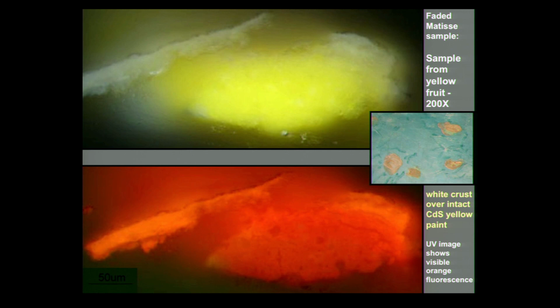And then here's a look at a tiny flake of paint that we removed from one of the yellow fruits in the tree of the Joy of Life. And you can see that there is a white degradation crust forming on the surface of an actually very intact bright yellow paint. And when we look at this same paint cross-section in ultraviolet light, it has this characteristic crazy orange fluorescence that you see for cadmium yellow as it starts to degrade.